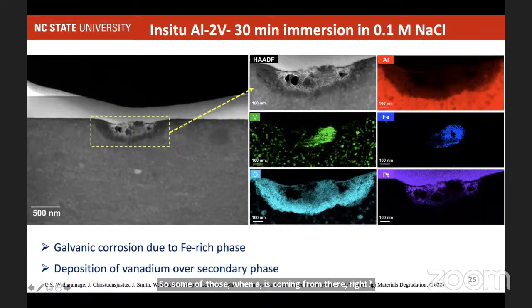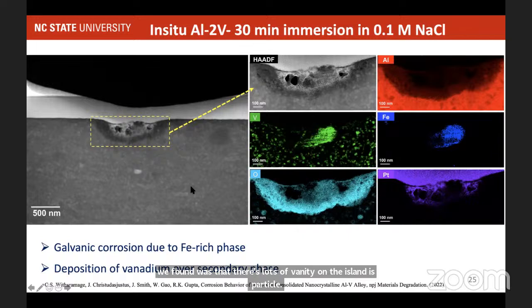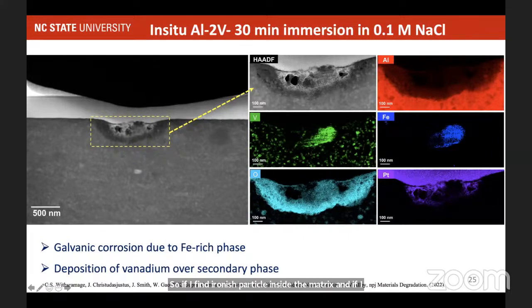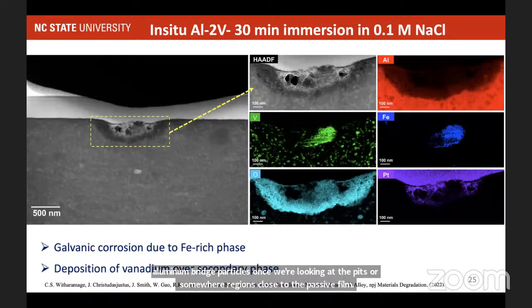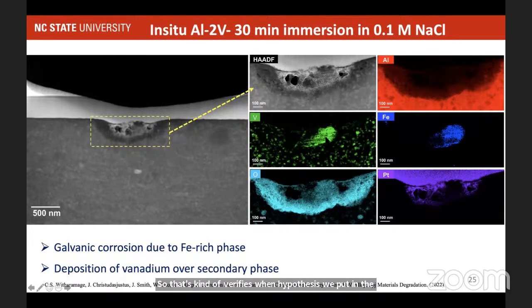Now we detected that, and another thing we found was that there's lots of vanadium on that iron rich particle. So if I find an iron rich particle inside the matrix, and if I do the EDX analysis, I won't find vanadium and aluminum together, but we always find vanadium on top of these iron rich particles once we're looking at the pits or regions close to the passive film. So that verifies one hypothesis we put in the beginning when we were designing the alloys, that the vanadium would be dissolving inside the pit, and it makes the vanadate, and vanadates are very well known corrosion inhibitors, right? So what those vanadates do is basically they deposit on those iron rich particles, and as they deposit on the iron rich particles, they shut down their cathodic activity.